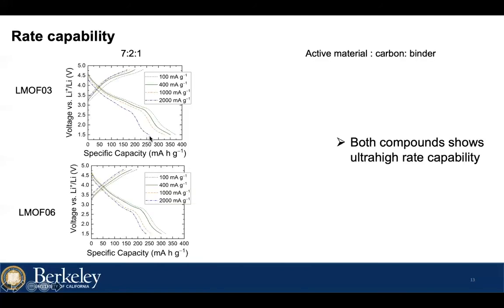After proving this partially disordered spinel structure can deliver high capacity at normal rate, we start to think about the high rate performance. Because we have already suppressed the kinetically slow two-phase reaction, and this spinel structure is favorable for lithium transport, we should get high rate capability from these two materials. After measuring the voltage profile at current densities ranging from 100 milliampere per gram to 2000 milliampere per gram, you can see the capacity only drops around 30%. It means that this material is able to deliver around 250 milliampere hour per gram capacity at a current density of 2000 milliampere per gram.